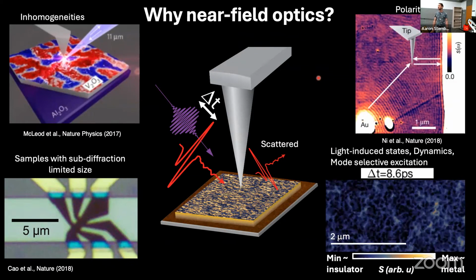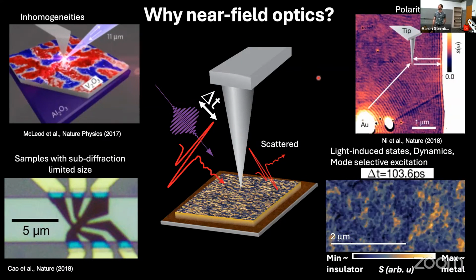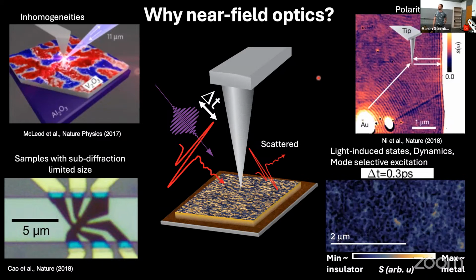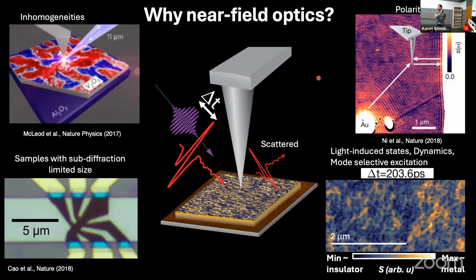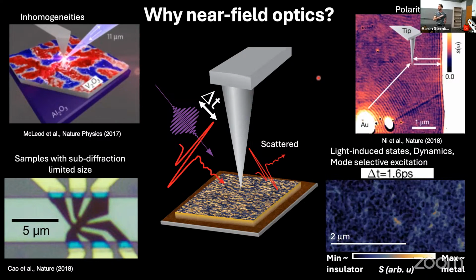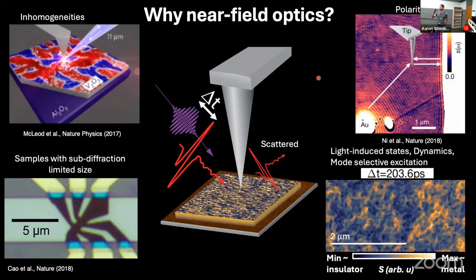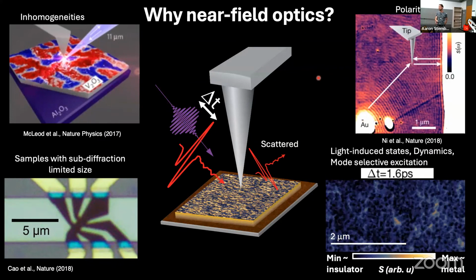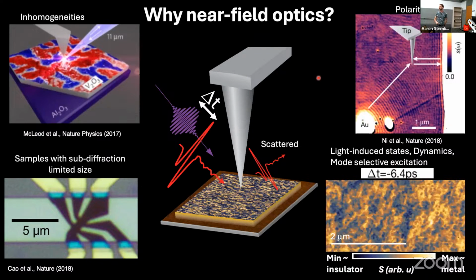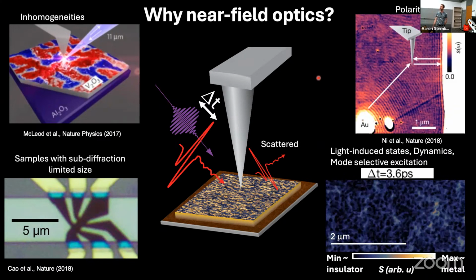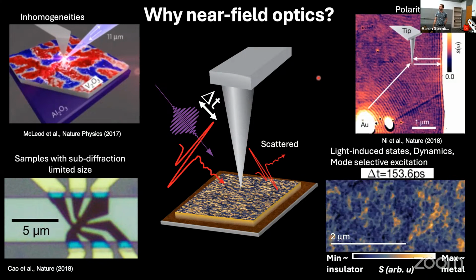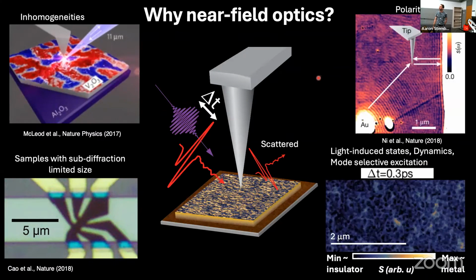If you take the Fourier transform of that evanescent field, you get components at high momenta. You're talking about frequencies, but the frequency is fixed by the incident field. We're not changing the energy in this experiment. It's not a nonlinear experiment. There are components of the momentum which extend to much higher momenta. So the actual peak of momenta that we're sensitive to is 2 pi over the radius of curvature of the tip. And so this does extend to higher momenta, but the frequency is fixed. We're way away from the light cone, is maybe the way to say it.